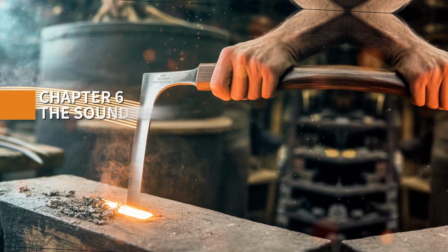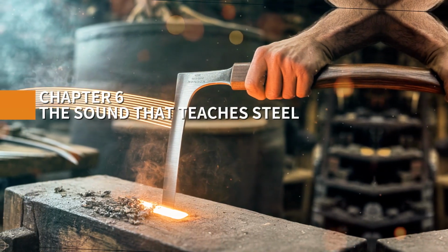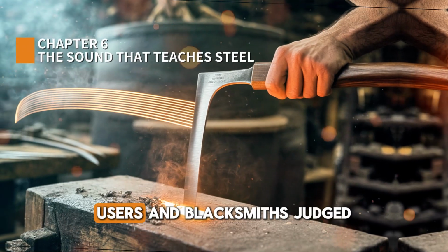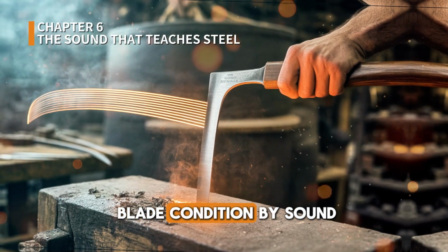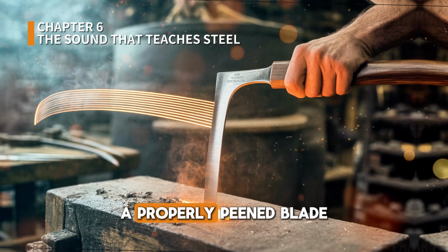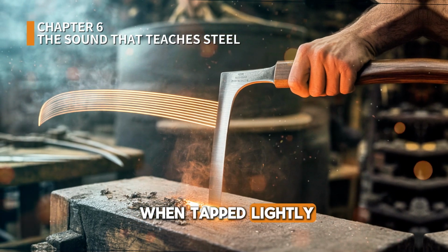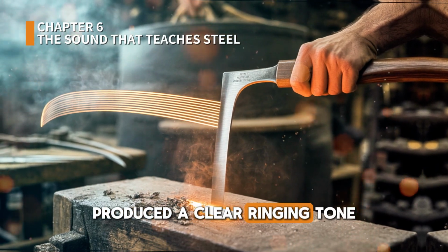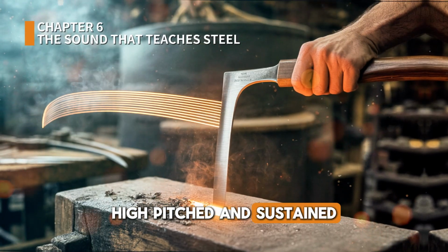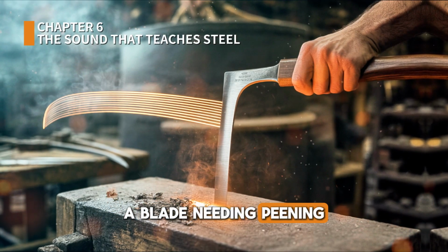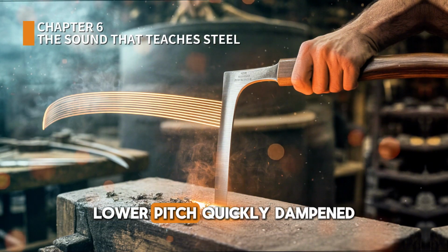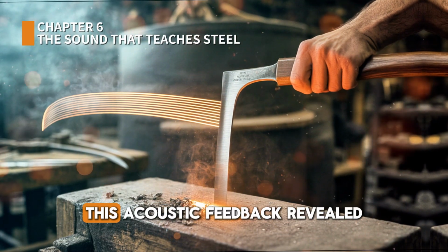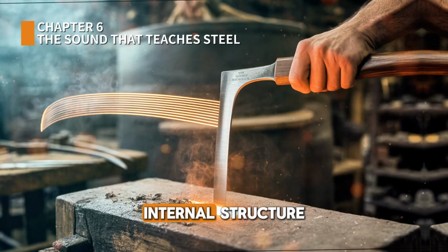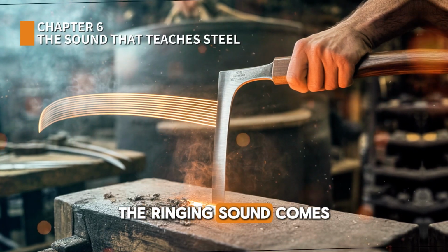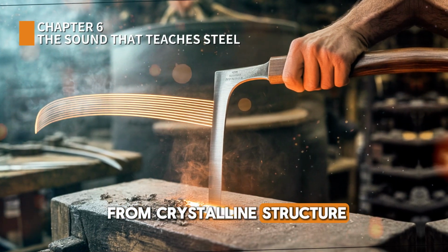Chapter 6. The sound that teaches steel. Experienced scythe users and blacksmiths judged blade condition by sound. A properly peened blade, when tapped lightly, produced a clear, ringing tone, high-pitched and sustained. A blade needing peening produced a duller sound, lower pitch, quickly dampened. This acoustic feedback revealed the blade's internal structure. The ringing sound comes from crystalline structure vibrating.